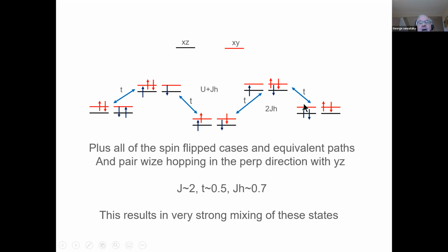And then you have basically a reduced magnetic moment on each atom. And the reduction of that magnetic moment is going to be extremely sensitive to the parameters. So that is the electron phonon coupling or electron lattice coupling, which is all horribly sensitive to interatomic distances and to orbital ordering, of course. And this could even result in orbital ordering, but of a complicated kind, of an orbital exchange type of process between atoms. I think this is something that Daniel had also mentioned, or maybe other people. So I think these kinds of things are really important fluctuations, also fluctuations which can lead to pairing, okay?